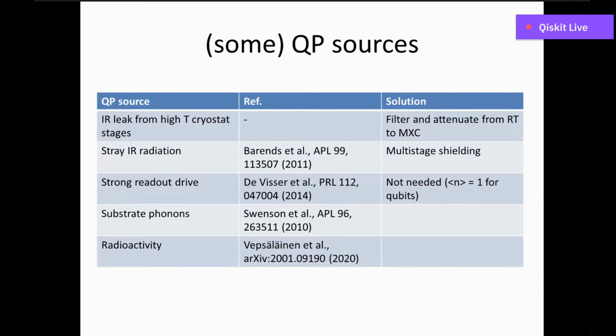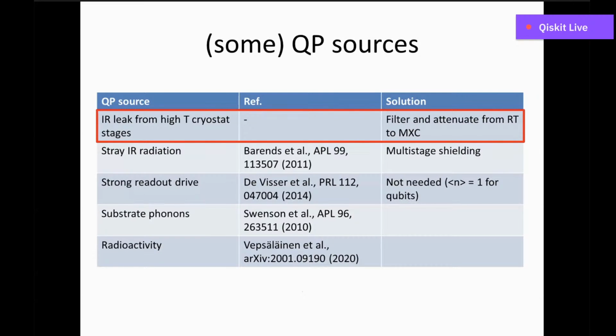Then, if quasiparticles are our window on the effect of radioactivity, another step that we have to take is to make sure that the quasiparticles that we see are only due to radioactivity and not from other sources. Let me briefly go over some other quasiparticle sources. The more obvious one is radiation leaking from the wiring in my cryostat. We make the effort of cooling down our superconducting circuit, but then we have this coaxial cable that goes all the way to room temperature. We don't want heating coming down from this line, creating excess quasiparticles. The solution is to filter and attenuate RF lines in cryostats, and we take care of this.